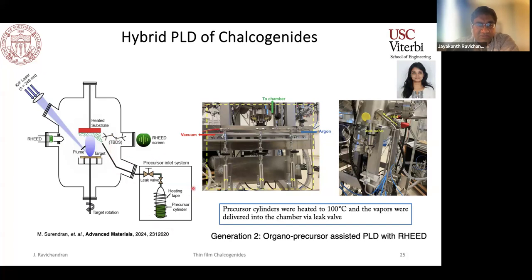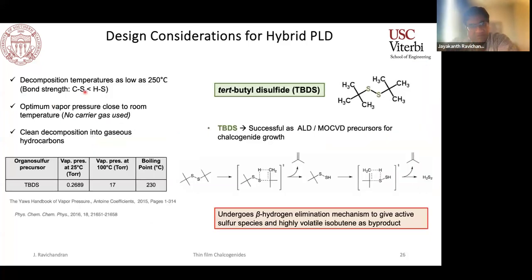And we designed a very simple zero generation precursor inlet system. And this is work again, Maithili published a year ago, where we were able to create this hybrid PLD technique where our pressures in the chamber are not as high as what you would have with argon H2S. It's mostly flooded by this precursor, and then you can do the growth as usual that you would do for a PLD system. Now, there are some design considerations for this. What sort of precursor do you choose and why?